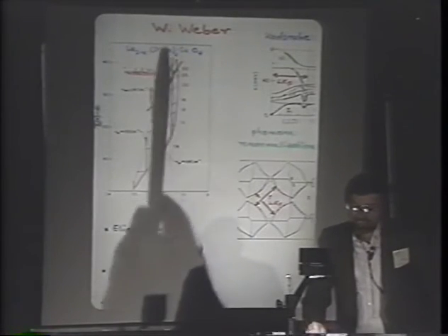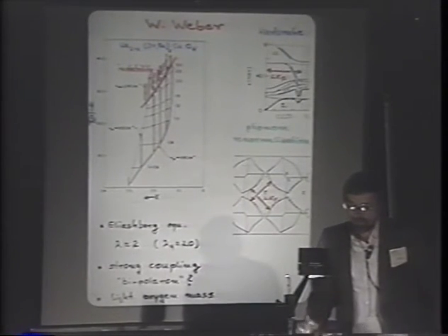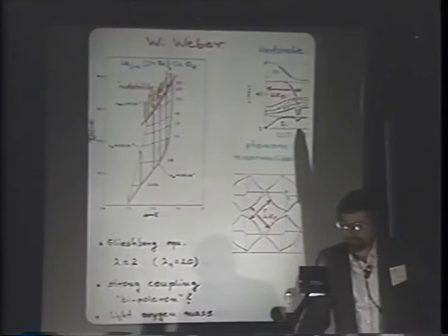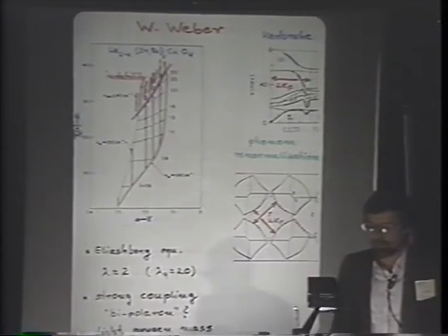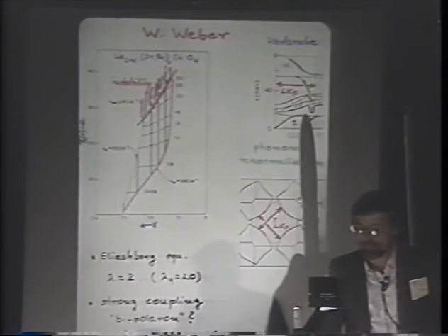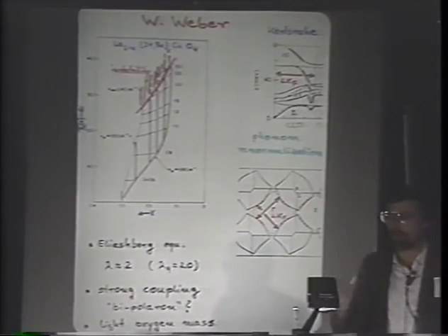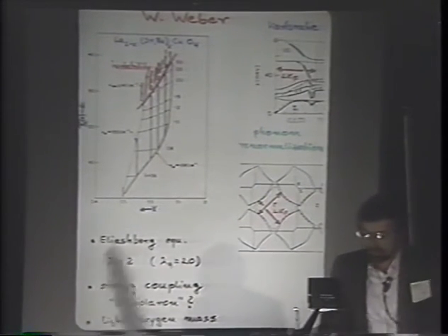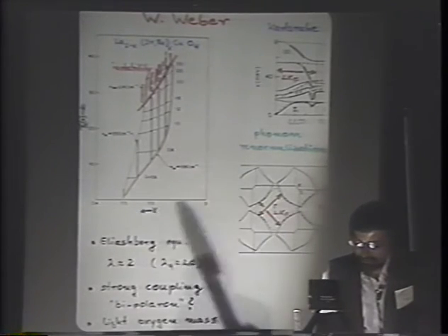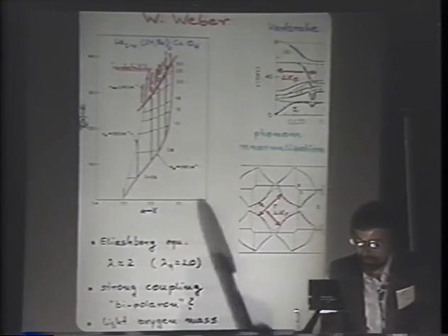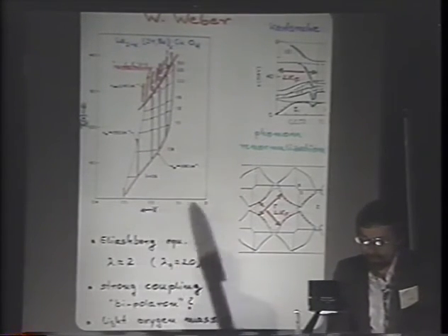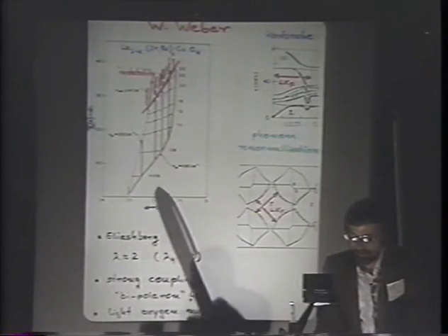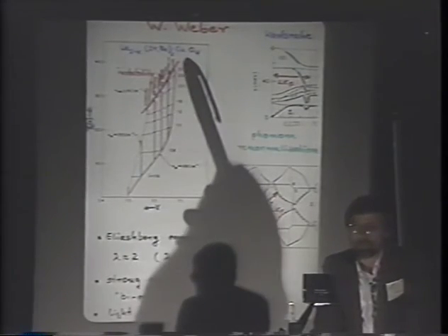Now, Weber calculated phonons in these materials. In fact, if he uses the pure material, the material becomes unstable. So he has to dope it. If he dopes it, he moves the Fermi level slightly out of this perfect nesting condition, and he finds drastic phonon softening. If he does these calculations for all points in K-space and solves a Eliashberg equation, he can calculate Tc. This is shown here as the yellow curve as a function of doping. As you dope out of the range where the material becomes unstable, you run into high Tc. It is unstable up here and over here, but as you dope out of this range, you run into high Tc of order 40 degrees for these materials.